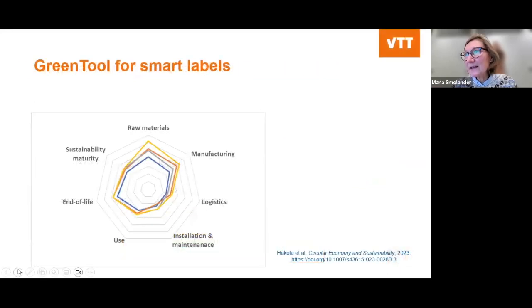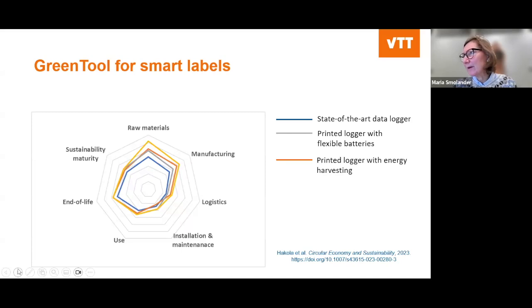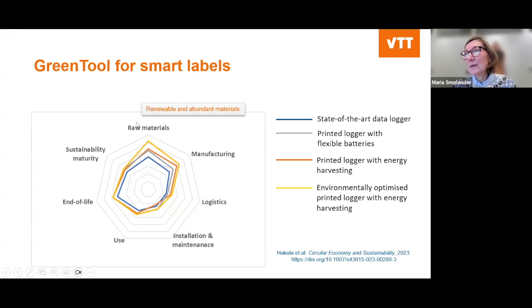And we have done this for the smart labels. This has been explained in the same paper where we explain the methodology. In this case, we were comparing the state-of-the-art data logger with a printed logger with flexible batteries, a printed logger with OPV-based energy harvesting, and then the same one but with environmentally optimized materials. And here what we could see is that regarding raw materials, where we could see the biggest differences, the differences come from the possibility to use renewable abundant raw materials in manufacturing. The difference comes from additive manufacturing. In logistics, mainly from the lower weight and possibility for non-distributed manufacturing.